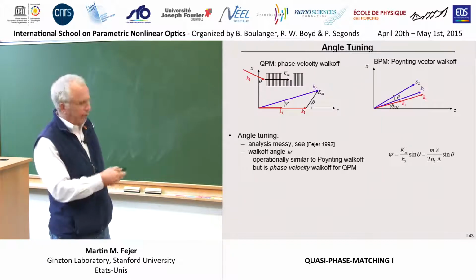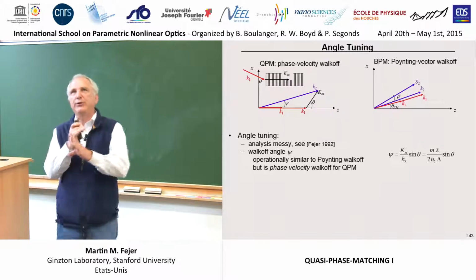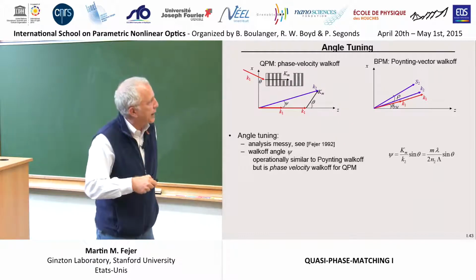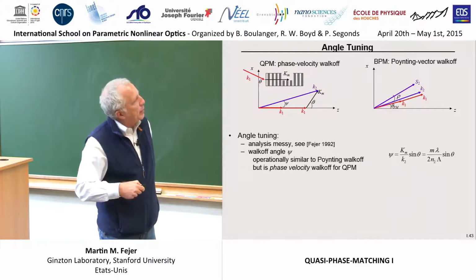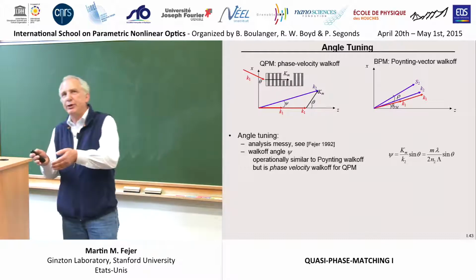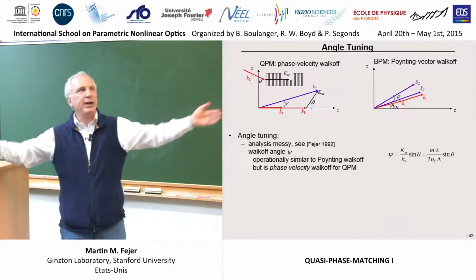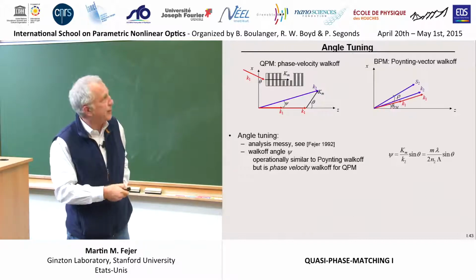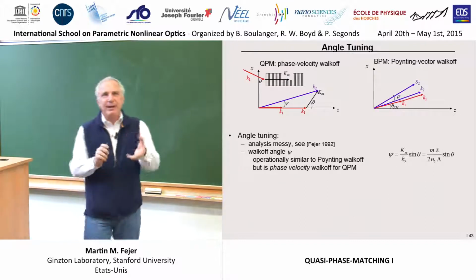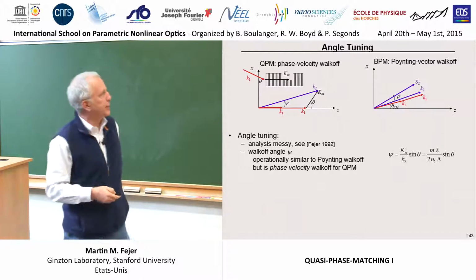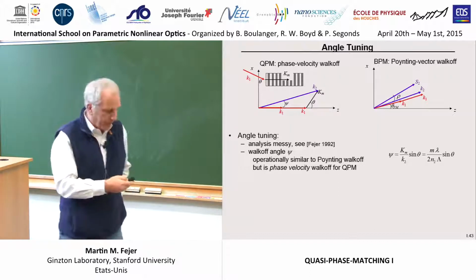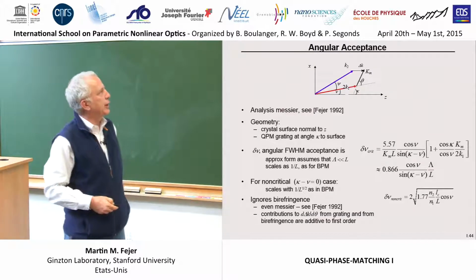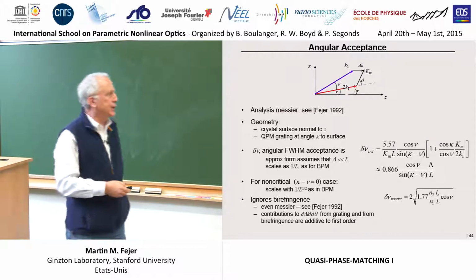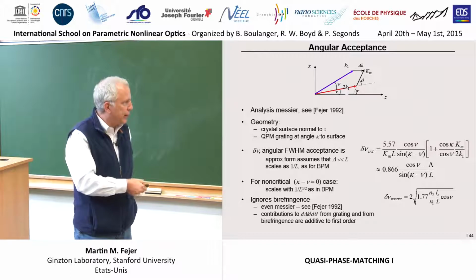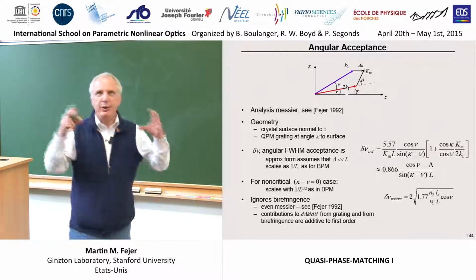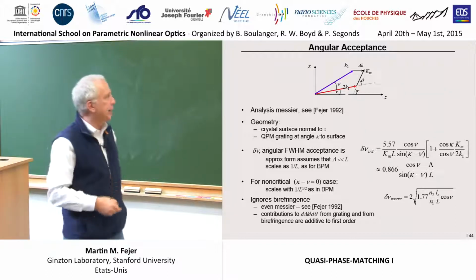If you remember the Poynting vector case where you did critical phase matching in a birefringent crystal, the K vectors lined up, or at least they did if your drawing was better. But because the Poynting vector was not parallel to the K vector, you had separation again of the harmonic and the fundamental, but this was a group velocity effect rather than a phase velocity effect. So we'll report back if we ever agree on what the right answer is for this tuning behavior. Let's not go into those expressions. They're not crucial. You can do angular acceptance expressions. Again, the details are in this paper. As I say, these little short notations are expanded in the bibliography if you want to track that down.